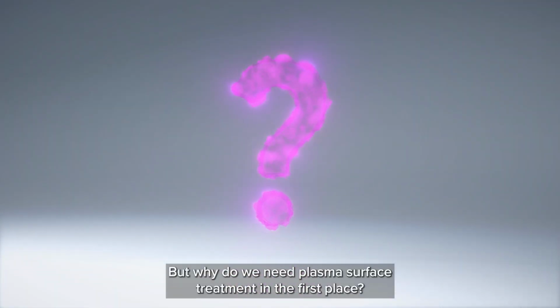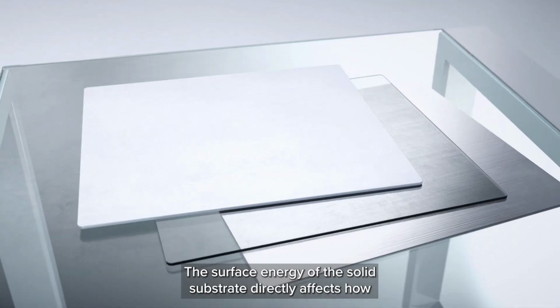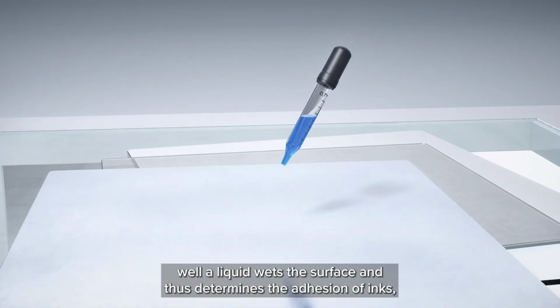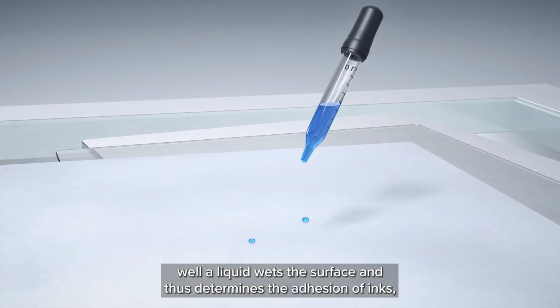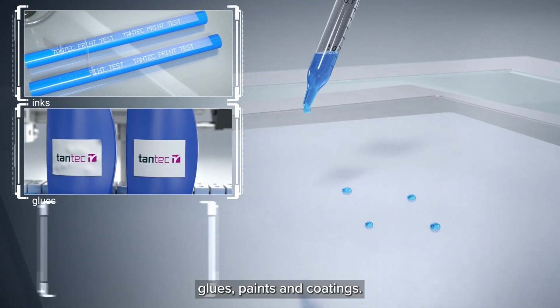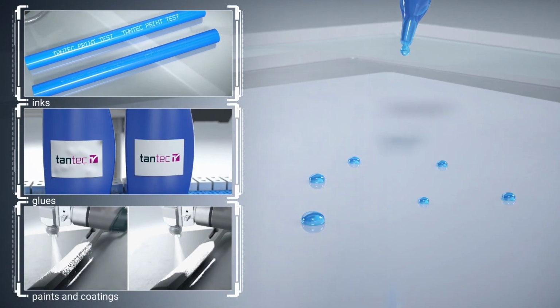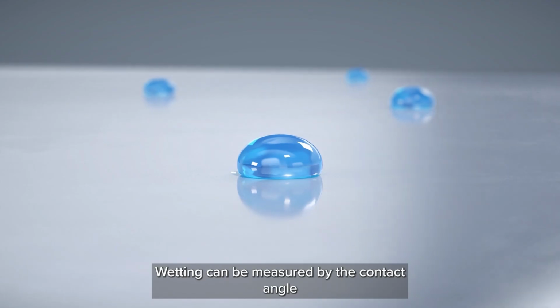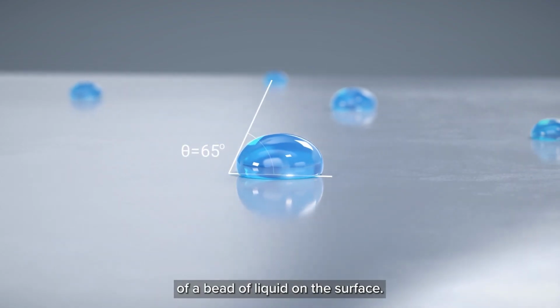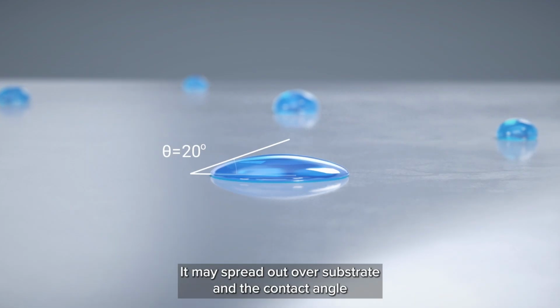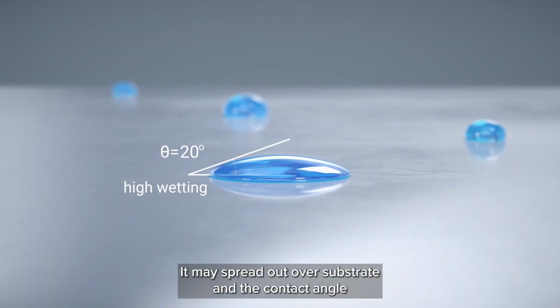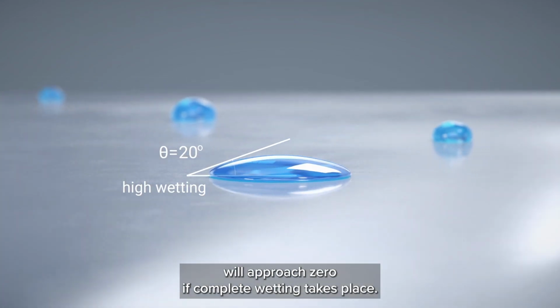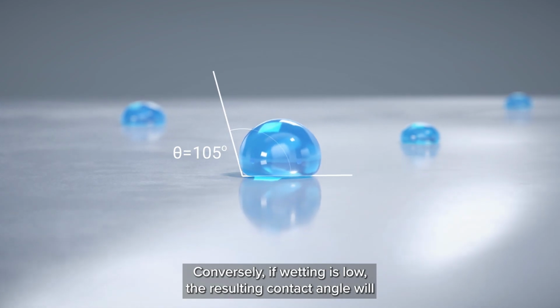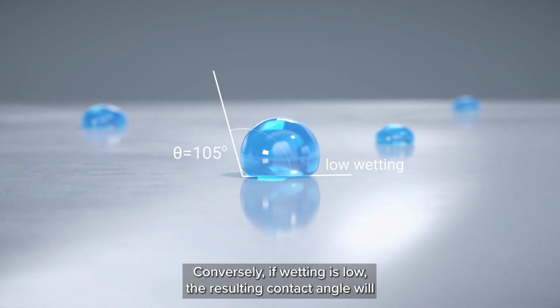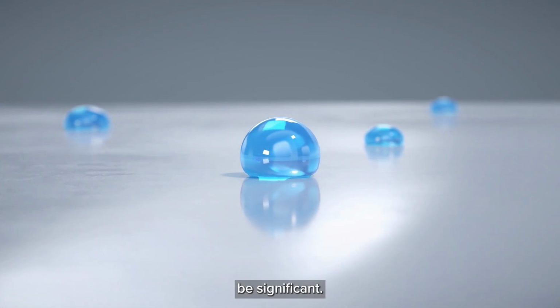But why do we need plasma surface treatment in the first place? The surface energy of the solid substrate directly affects how well a liquid wets the surface and thus determines the adhesion of inks, glues, paints, and coatings. Wetting can be measured by the contact angle of a bead of liquid on the surface. It may spread out over the substrate and the contact angle will approach zero if complete wetting takes place. Conversely, if wetting is low, the resulting contact angle will be significant.